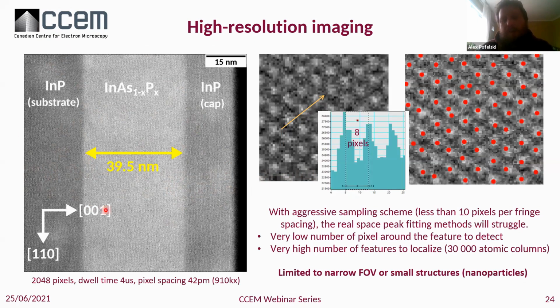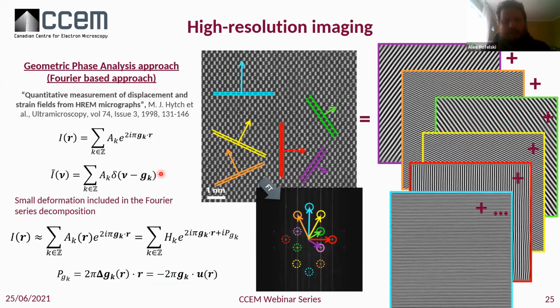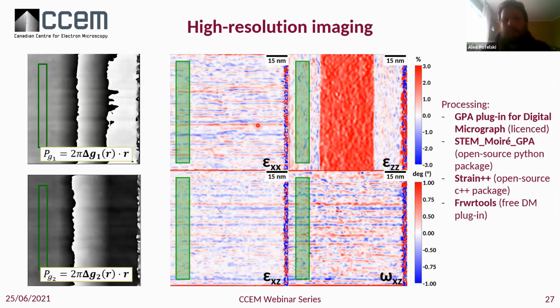This is because the noise profile is preferential in that direction rather than in the out-of-plane direction. So we have a tendency to align the direction of deformation, where we expect it, towards the in-plane direction. So that's why I rotate this, to limit the scanning noise. We can actually see the scanning noise here, as you see. So if you rotate the image and you invert X and Z, you will have on top of that this noise profile.